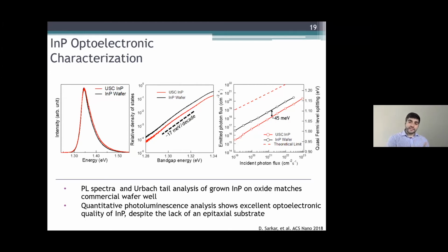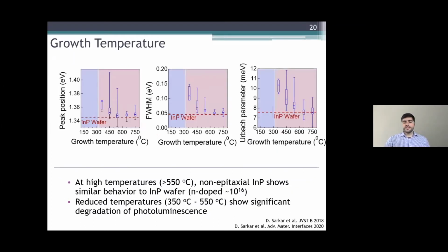And what that tells us is that because we can grow single crystalline domains, even though it's non-epitaxial, we can actually start to achieve performance much better than what you could get if you just deposited a material using a standard vapor phase growth technique. Now, the challenge is that most of the stuff I've been talking about so far has been grown at maybe 500, 600, even up to 700 degrees C. And when you do that, what you actually get is pretty good quality material. And so that's what I'm showing here.